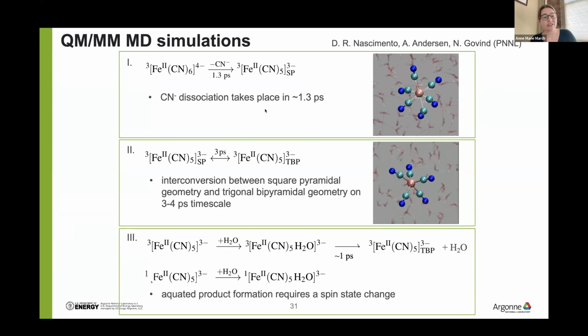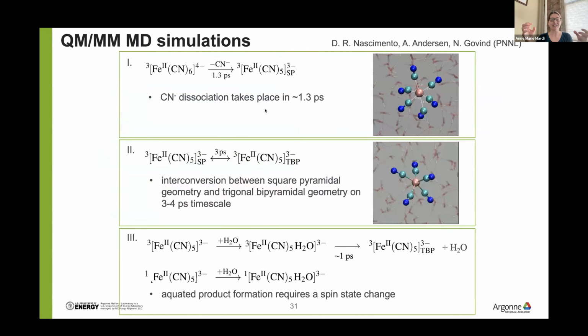Then they looked at what happens to this triplet square pyramidal pentacoordinated species, and they found that it will fluctuate, but it's between the square pyramidal geometry and the trigonal bipyramidal geometry, and it will fluctuate between the two geometries on a time scale of about 3 to 4 picoseconds. Then if they bring a water in close, when the pentacoordinate is in a triplet state, it'll just spit it right back out. What needs to happen, the water needs to be close, and there needs to be a spin change for the water to stick. And so they showed that.